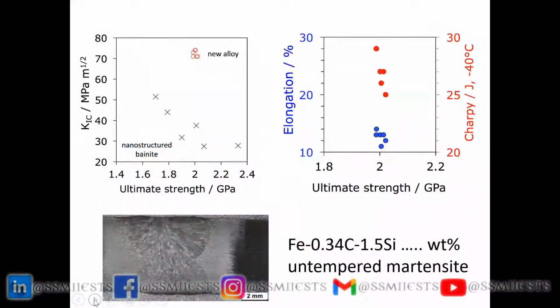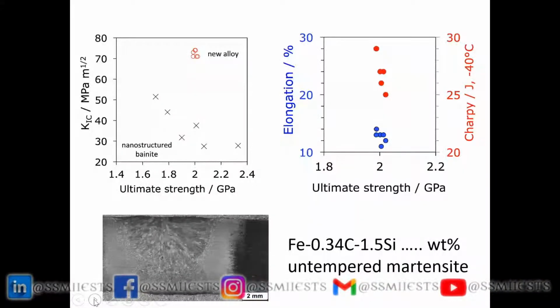This turns out to be a really remarkable material. So there's no problem at all with welding it, right? Even though it contains 0.34% carbon. This is arc welding. Laser welding has been tried, but it's not a practical tool for making structural components. And if you look at the toughness, and the crosses there are for nanostructured bainite, and the new material here systematically has a toughness of about 75 megapascal root meters. And if you look at the Charpy results at minus 40 degrees centigrade, you've got impressive Charpy results and elongation.